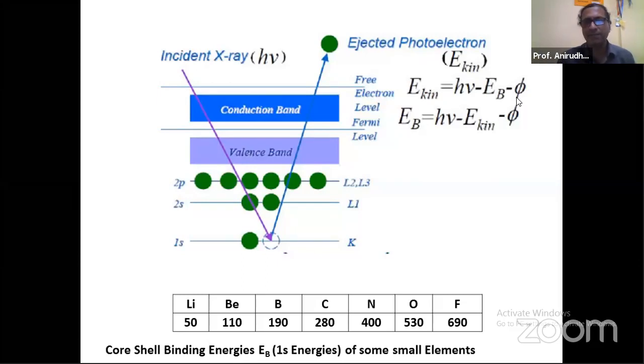So from which we can calculate, if we just rearrange that equation, the binding energy EB will be equal to h nu minus E kinetic, that means the kinetic energy of this electron, minus that constant term, which is phi, which is a calibration parameter specific to the equipment. Now our interest is in this EB. Now how can we get this EB?